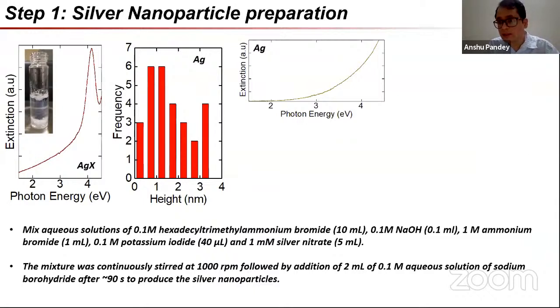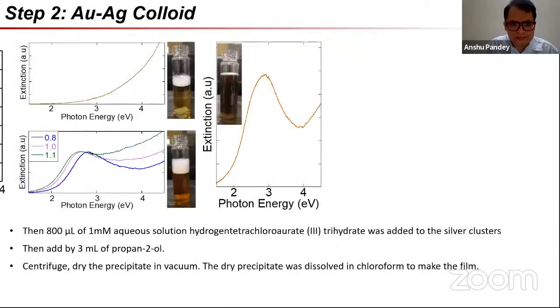So here we are getting the silver halide particles forming. This is step 1. So we are getting silver halide particles, around 1 nanometer in size, or at least these are what lead to 1 nanometer size silver. I don't know the size of the halide. We have never measured that. So these are still all in solution.